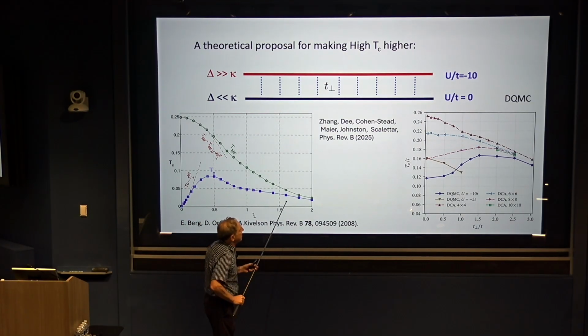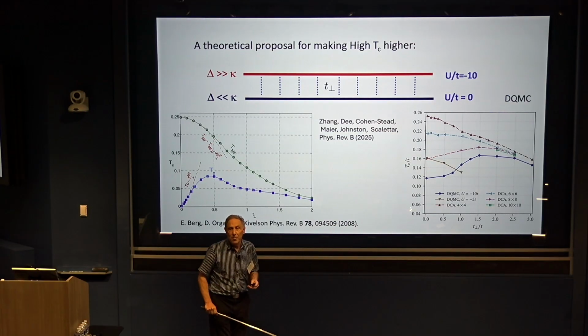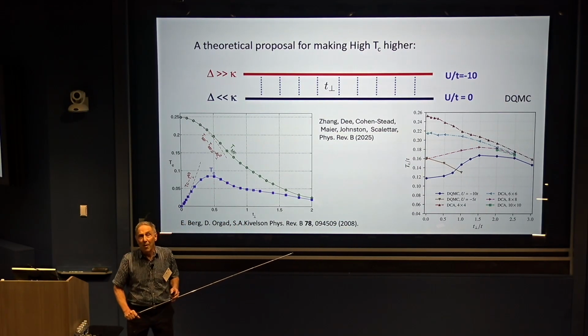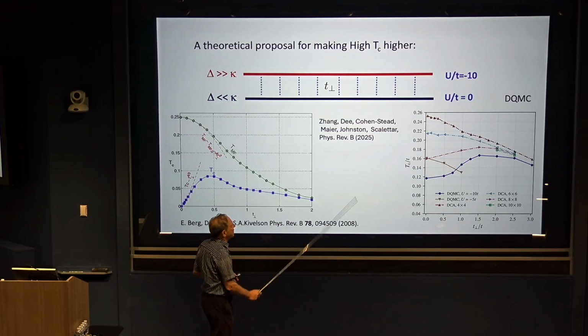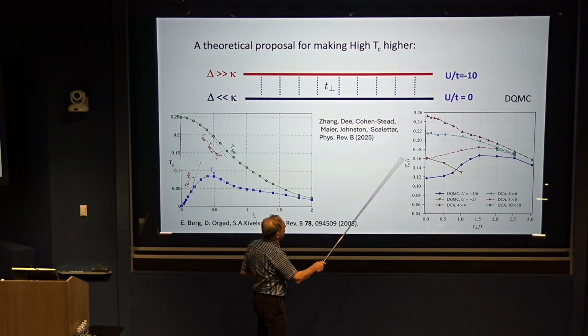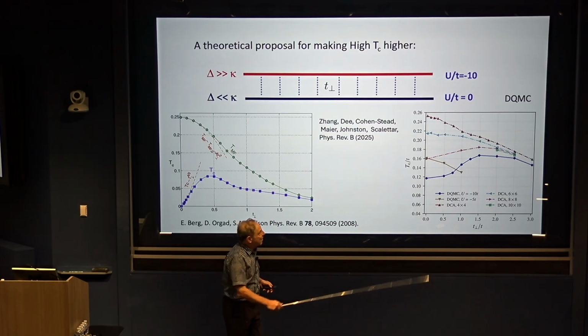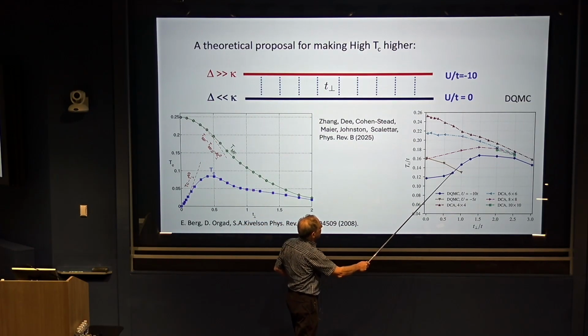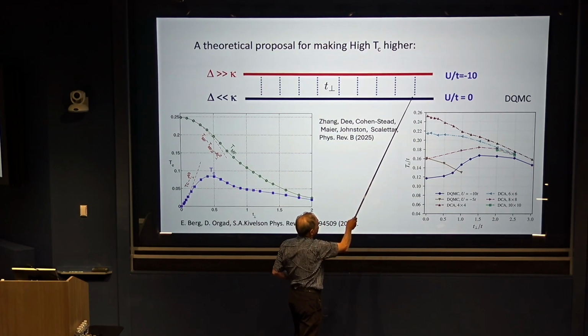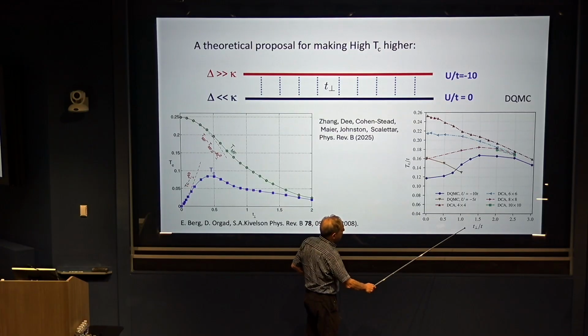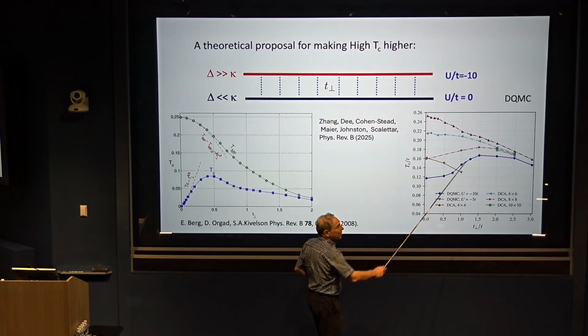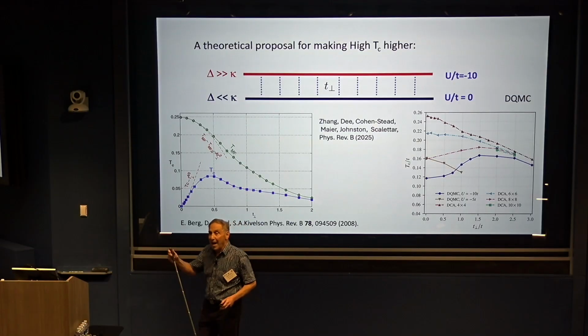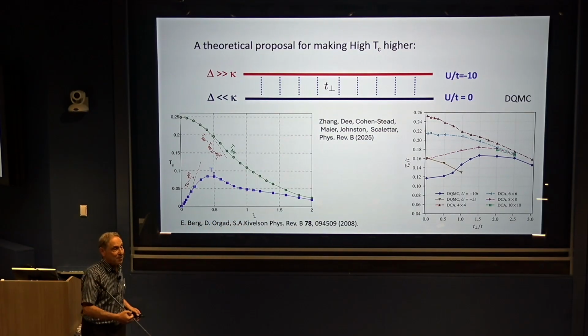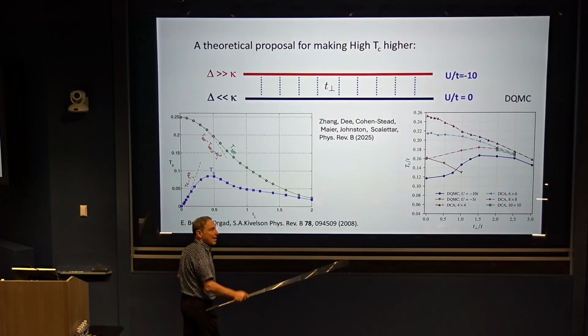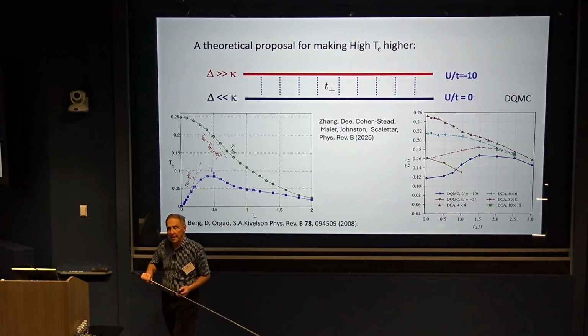More recently, the negative U Hubbard model can be solved by sign-free quantum Monte Carlo calculations, which was done by these gentlemen. They didn't take quite as extreme parameters as we did, but if you, for instance, look at this blue curve, which is for U equals -10 on this layer and 0 on this layer, you can see that as you turn up T perpendicular, you actually get, indeed, an optimal value at which TC is maximized. So in theory land, at least, this idea works.